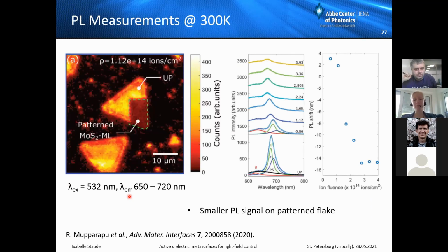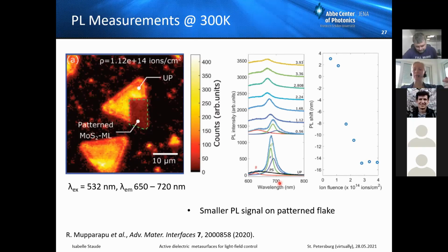Yeah, so this is now a bit hard to assess. Here you see the spectra, and it's rather not blue shifting, and also I would say broadening a bit, but we also introduce, as the ion fluence increases, more and more damage. So it would not be a pure experiment to look at straining properties here. Rajesh went through quite a complex model to try and fit all these points, taking doping and strain and so on into account. But this damage is hard to account for, and at some stage the ion fluence is so high that you lose the peak. So we expect some broadening, and therefore we cannot analyze the width of the peak just as a consequence of strain or release of strain.